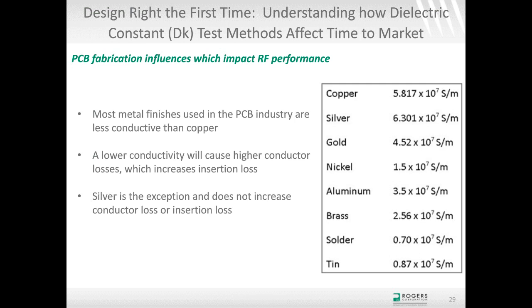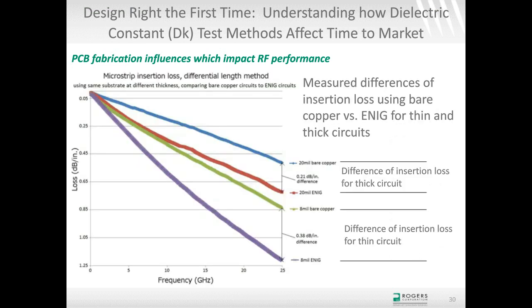And here's a good example of the influences of plated finishes being related to circuit thickness, and there's also a circuit design relationship. But here I'm looking at the exact same circuit design. It's microstrip transmission lines using the same material. It's RO4003C laminates, and in this case, I had circuits built on 20 mil thick laminate, and also had circuits built on 8 mil thick laminate. So I'm showing differences in the substrate thickness. I'm maintaining 50 ohms for the microstrip transmission lines, and I'm comparing bare copper to ENIG.